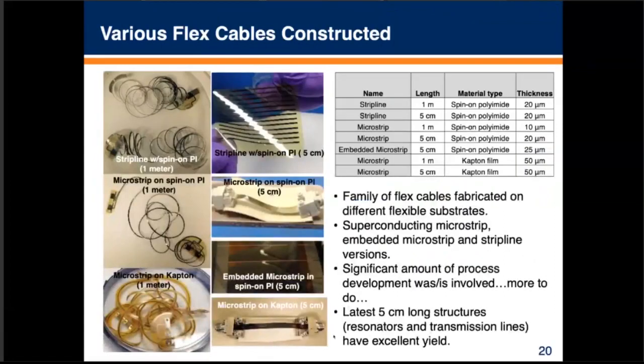So over the years, we've made a pretty wide array of different types of superconducting flex cables. You can see those all listed out here: microstrip, embedded microstrip, and strip line, from a few centimeters up to a meter using Kapton, as well as the thin film processes that I mentioned earlier. Some of those are shown here. So you can certainly make long spiraling structures on a 150 millimeter wafer and release that and have a nice 1 meter long strip line cable there.